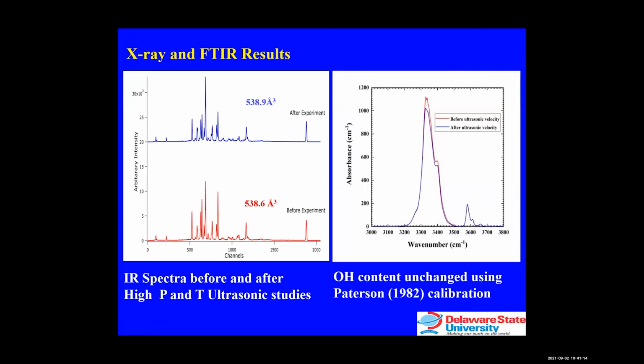We also show here the X-ray, and here we show the perfect match between the X-ray diffraction pattern and the unit cell volume taken before and after the high pressure and high temperature ultrasonic experiments, showing that the integrity of the sample is actually maintained during the experiment. Also, on the right side we show that there is no water loss from the sample, as shown by the FTIR spectra of the sample before and after the high pressure experiment.